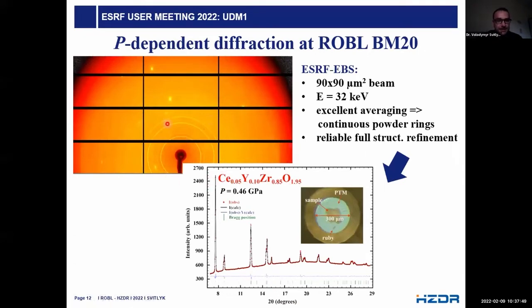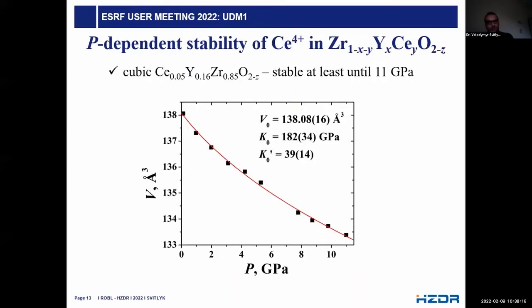We have excellent averaging of powder rings, they are fully continuous. And you are able to reliably perform full structural refinements. This is one example with agreement factors on the order of a few percent. And I must say, we didn't observe any kind of parasitic signal, neither from the gasket nor pressure markers, up to the highest studied pressures. So I will briefly show you two examples.